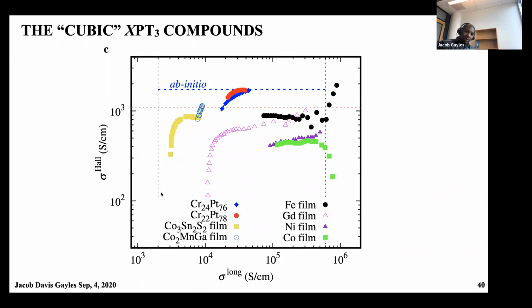And then on the left, what you have are these topological materials, which are cobalt-tin-sulfide and Co2MnGa. The Co2MnGa and cobalt-tin-sulfide have a very low conductivity, and this is due to this Weyl semi-metal dispersion, where you have a very low density of states in the electronic band structure.